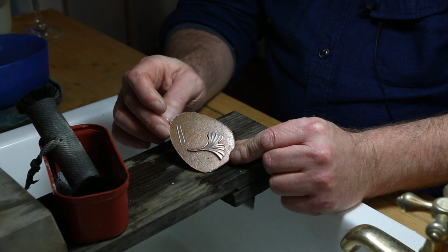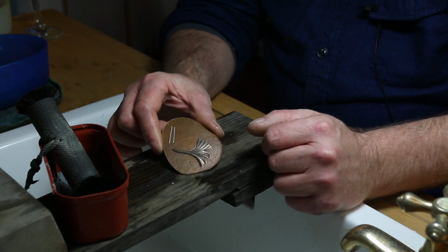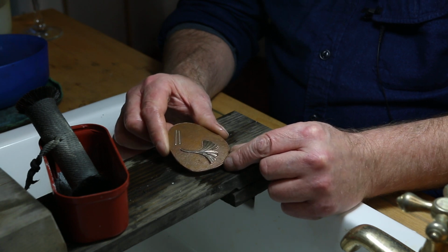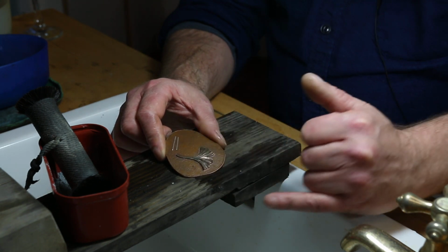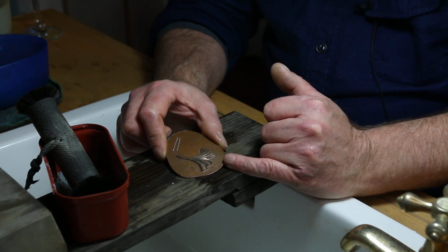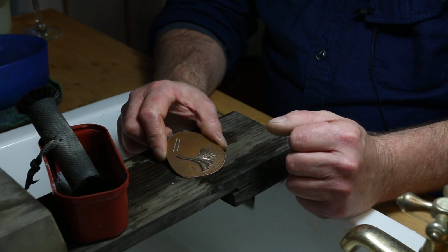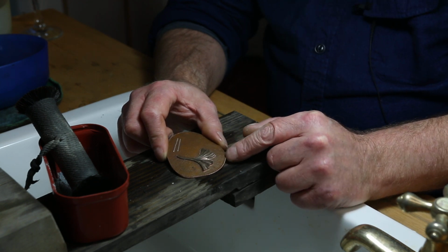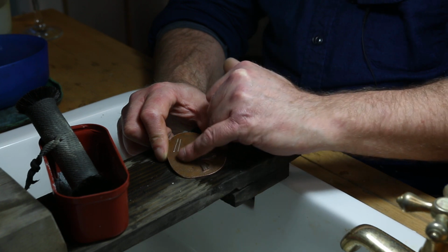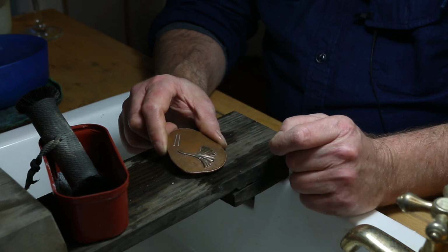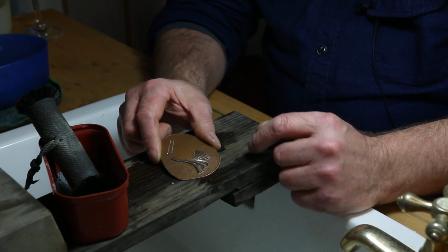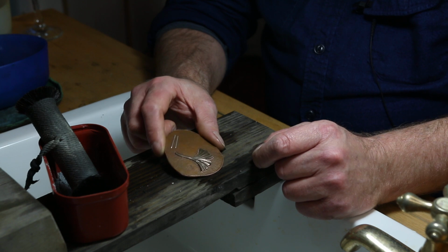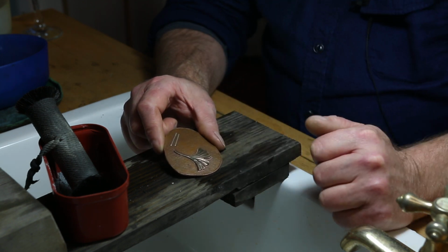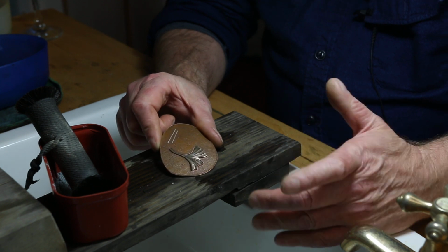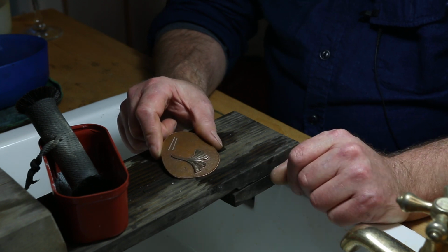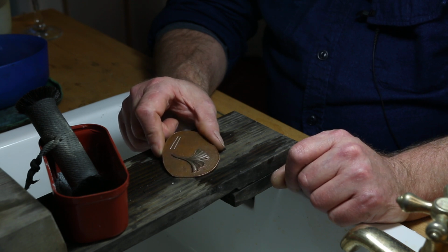You might be tempted, if you're a jeweler or have some experience with jewelry technique, to pop this in the pickle. I don't like to do that. There's a number of reasons. The main one being that although you'll remove all the oxides, you're then left with a thin film of broken down oxides on the surface. And while you may polish many of them away, you still get little pink residues in the recesses, which when you come to patinate, don't take a color. So I rather prefer to mechanically polish everything clean. I can also that way see where I still need to work, whereas had it gone in pickle, everything's nice and pink and clean, and it's very easy to get the false impression that the metals are ready for patination.